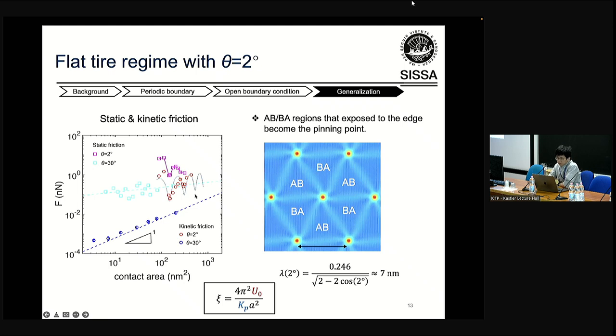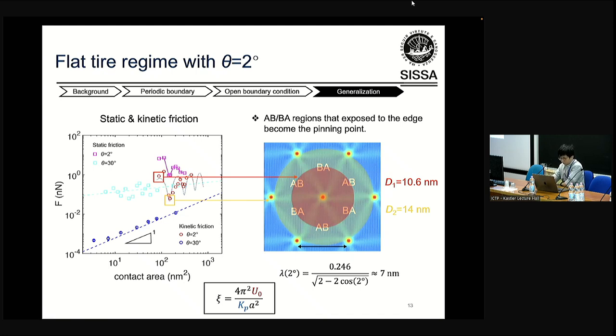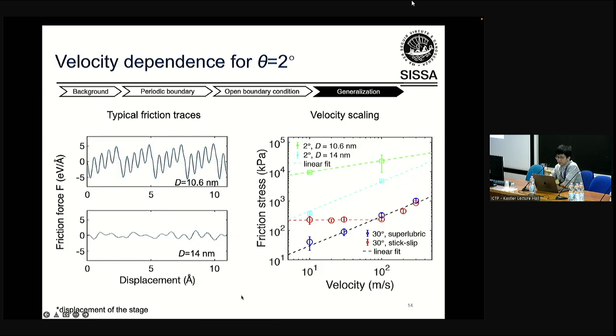The reason for this fluctuation behavior is that the AB and BA regions exposed to the edge become pinning points, which give rise to large kinetic friction. We pick two different sizes: local maximum friction at 10 nm (red) and local minimum friction at 14 nm. For the 10 nm case, the boundary crosses directly through the sixth AB/BA region. For 14 nm, all AB and BA regions are hidden inside the boundary. Since we can tune this boundary pinning effect by changing size, we no longer need to change kp. By fixing kp but tuning the size, we tune the sliding energy barrier and switch between stick-slip and superlubric regimes.